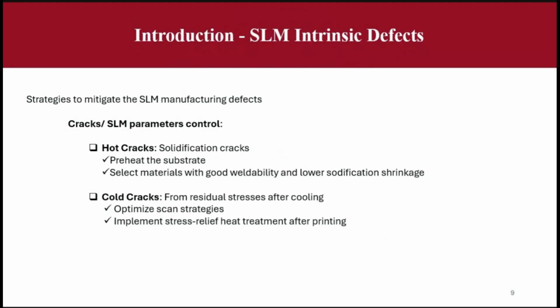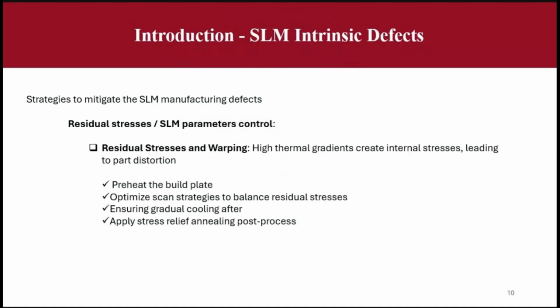So notice, you can manufacture very complex shapes. For each shape, you have a kind of recipe to make your components. For residual stress, you can prevent that by preheating the build plates, optimizing scan strategies to balance residual stress, ensuring gradual cooling after manufacturing, and applying stress relief annealing post-process.